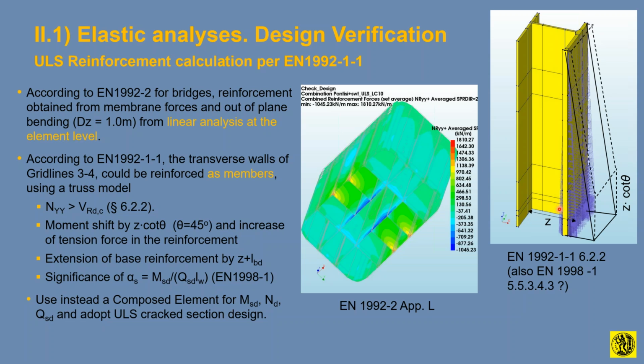However, if this is done, one would expect that after cracking, there is a moment shift, because this goes in the ultimate limit state with the truss analogy. In fact, Eurocode says that once you do a truss analog, you should shed half of the shear force into the longitudinal reinforcement, which resists parts of this shear. In fact, this is equivalent to the well-known moment shift. So one should move the typical moment diagram out of the unbalanced hydrostatic forces by lever arm times the cotangent of the angle. We accept theta is 45 degrees here. So we shift the moments.